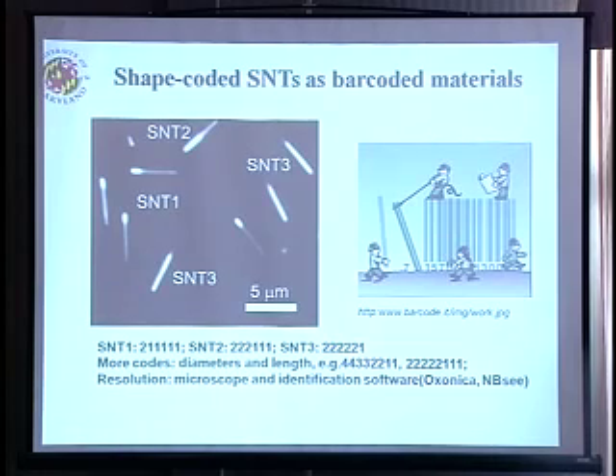So what does that mean? And very interestingly, previously what you saw was just the shape-differentiated nanotube structures in TEM images or SEM images. Certainly, you can distinguish the shape. But the more interesting thing is you actually can distinguish a whole lot of different shapes of nanotubes through the conventional optical microscope, because you have huge differences in reflectance values between the thicker part and thinner part.